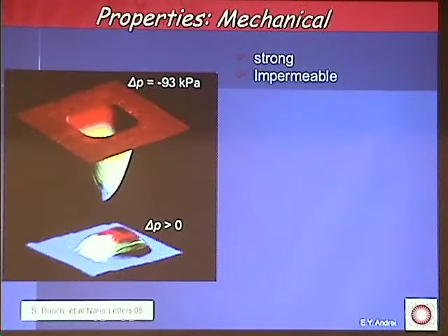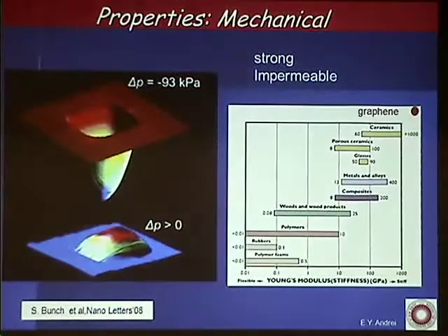So some of the properties of graphene. Let me start with mechanical properties. This is a graphene bubble that was blown up in Paul McEuen's lab. So there is a pressure. There's 1 atmosphere differential pressure on this graphene, 1 atom graphene sheet, and it blows up. And from the curvature here, you can figure out 2 things. First, you can measure the strength of the material, and when you go to Google, you can find a table like this. For example, steel would be here, various ceramics are here. Graphene is literally off the chart, and that is because of those sigma bonds.